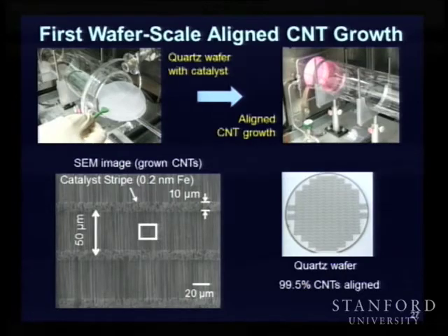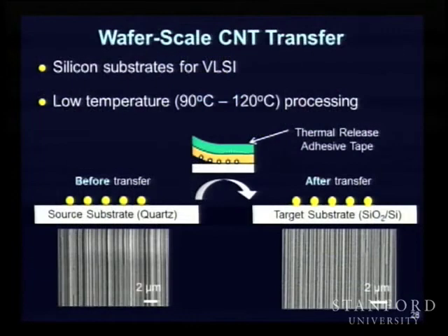But for silicon processing, you would want carbon nanotubes on silicon. And what do the students do? Well, they use a thermal release tape, almost like a sticker, to transfer carbon nanotubes from a quartz substrate to a silicon substrate at a full wafer scale. And this might sound funny, right? This looks almost like a hack, but this particular transfer step, we have found, is key to being able to achieve a lot of things.